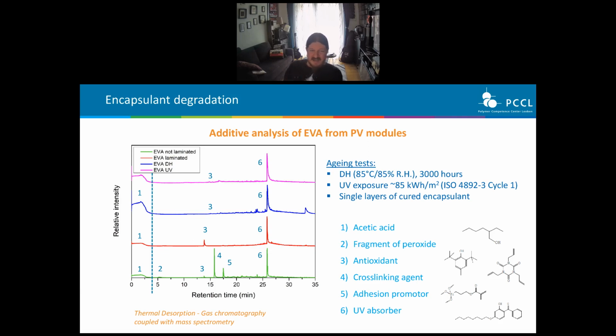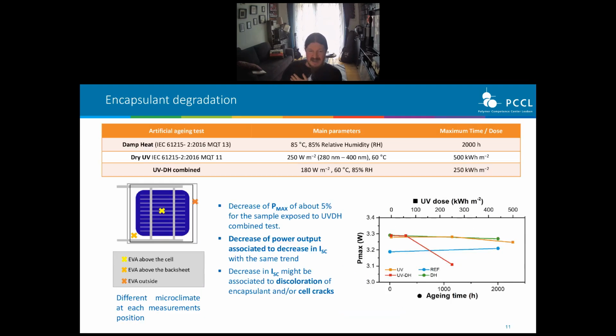Some of these additives are actually consumed during processing. You don't find the peroxide cross-linker or adhesion promoter anymore after proper processing. But it also happens that due to aging, due to UV exposure, for example, antioxidants or UV absorbers are consumed. In the next slides, I will show you how this affects the power loss of a PV module.